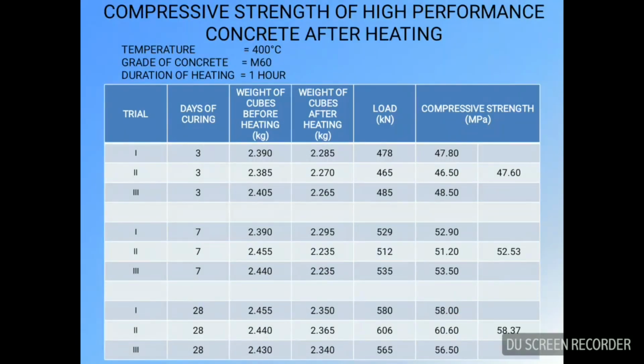M60 grade of concrete was heated at 400 degrees Celsius for a duration of 1 hour. The same procedure was used, and the compressive strength came around to be 47.6 at 3 days of curing, 52.53 at 7 days of curing, and 58.37 after 28 days of curing, which is still at 90% of our target strength.